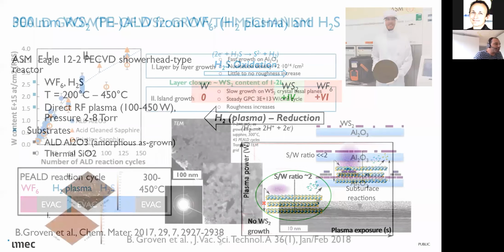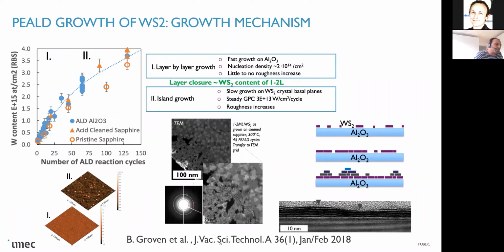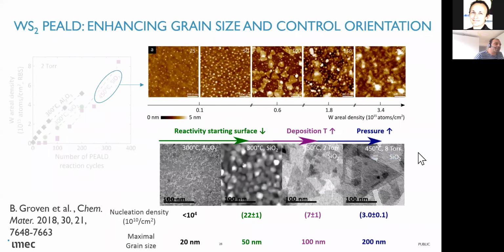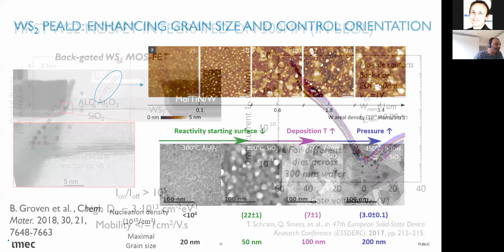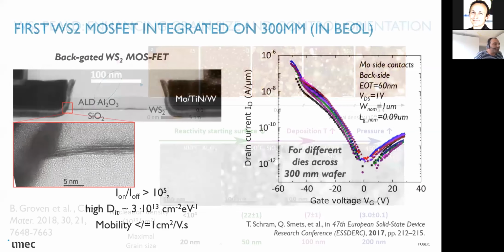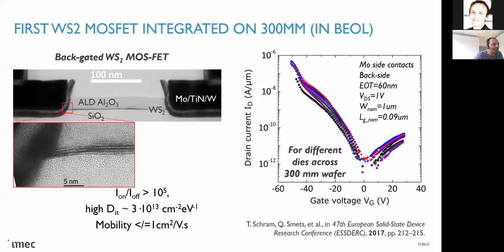We managed to grow relatively good quality material with some understanding, but basically we were limited by the reactor conditions and by the methodology itself to a grain size of 200 nanometer. And this is basically yielding a material quality, a mobility, of less than 1. So this is not something that is useful for CMOS applications. But nevertheless, it allows us to have a workhorse in the line and to do the first integration cycles on 300 millimeters.